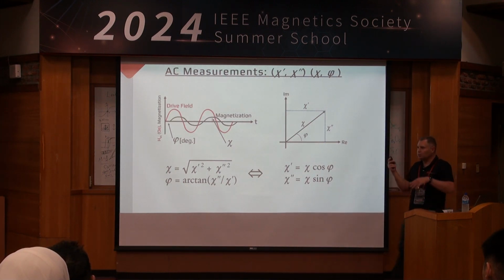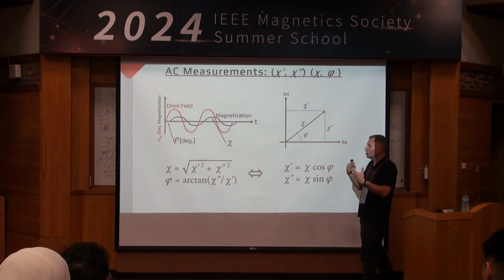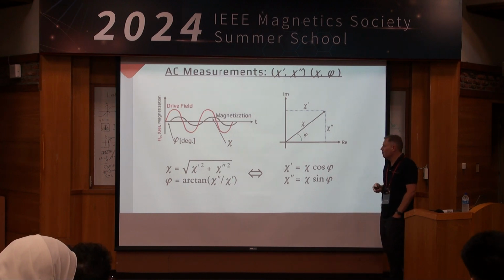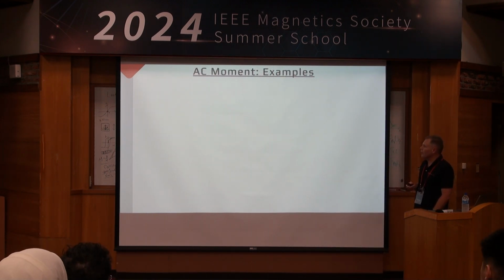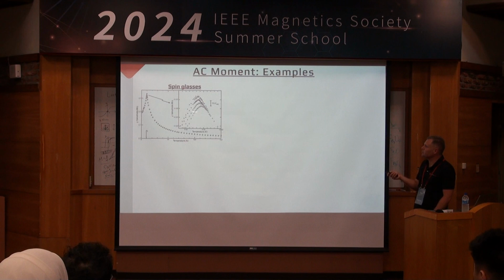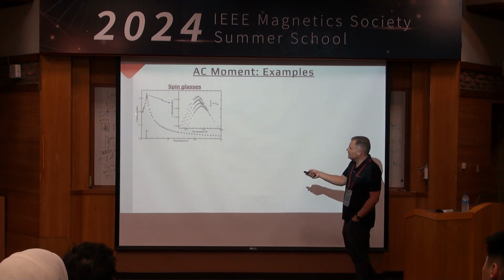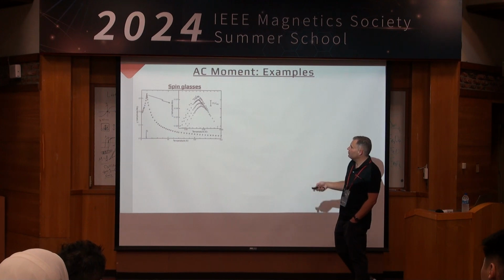You can go through the thought experiment where you go through a very slow AC field, in which case they'll just follow one another. That's when you're basically just measuring the slope of the DC response. And things get interesting as you go higher in frequency. So just some examples of the spin glass material here. AC susceptibility, the real component as a function of temperature. You get this cusp here, that freezing temperature.